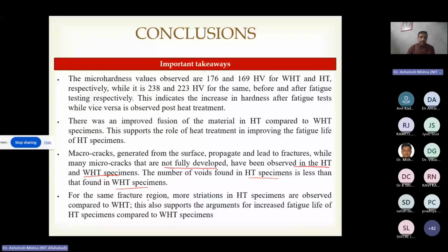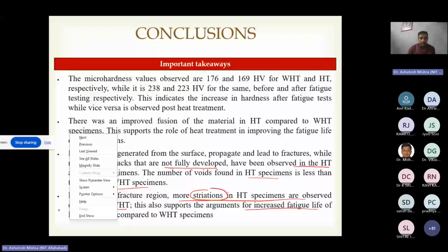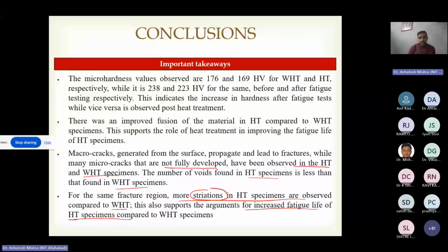Now, the number of voids found in the HT specimen is less than that found in the WHT specimen. HT again means heat treated, and WHT means without heat treated. For the same fracture region, more striations in heat treated specimens are observed. So striations are more compared to WHT. This also supports the argument for increased fatigue life of the HT specimen compared to the WHT specimen.